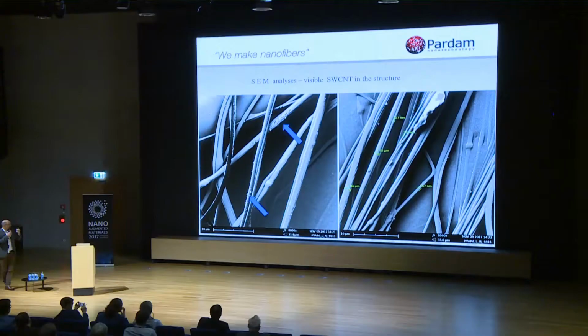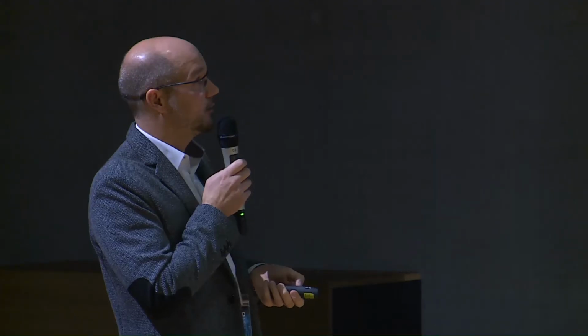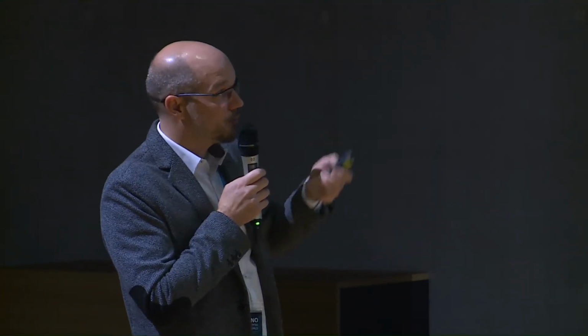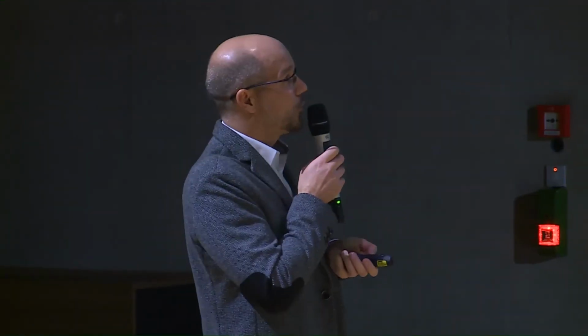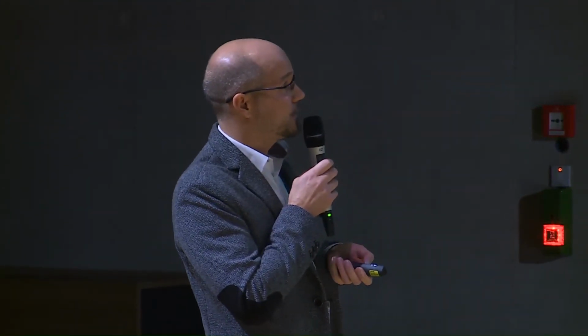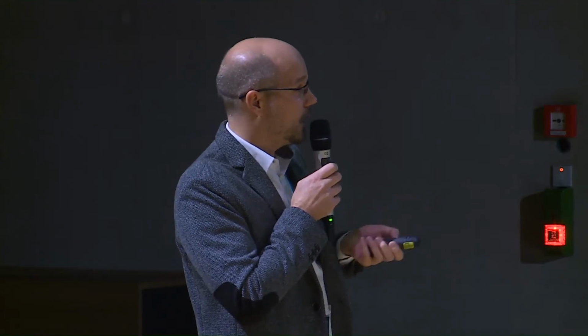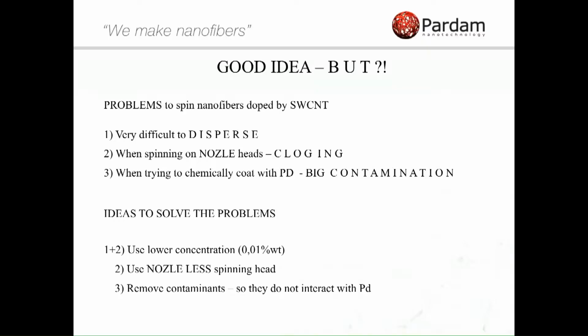Here we did some SEMs. We believe the particles on the fibers are single-wall carbon nanotubes. We need to do more tests and EDX analysis. But there is a promising way to functionalize the nanofibers with single-wall carbon nanotubes. And here are the ideas to solve the problem.